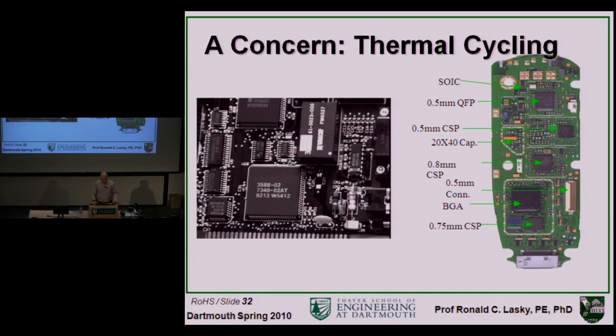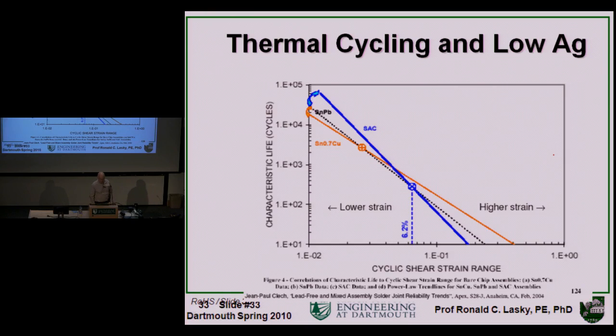So some work was done by my colleague Jean-Paul Clech, and I actually hoped to invite him here to speak to 103 about how he does modeling for data of this type, but he couldn't make it. But anyway, this is taking out the data points. This is tin lead, and this is how many cycles to failure, and obviously good is in this direction. And this is the shear strain range. And typically thermal cycling is in the lower strain. And if you look, this is SAC, this is the lead-free solder. In the data up to this time, SAC actually does a little better than tin lead solder. So for the historical thermal cycling type of performance that we were all interested in, it was better.